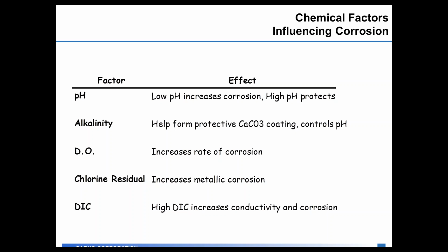Some other factors you'll look at are DO, dissolved oxygen, which would increase the rate of corrosion in your distribution system, and chlorine residual, or nowadays you also see chloramine residual. Chlorine residual specifically increases metallic corrosion in the system, and chloramine residual is less effective at removing biofilms from a distribution system versus free chlorine. So there can be differences in how those work in the distribution system.